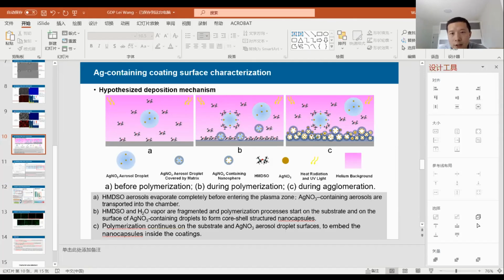For example, if we look at figure C, and look at the silver droplet, very close to the surface of the substrate, it's embedded very deep inside, so it takes more time. It's even harder for it to be released outside. So that's the reason for the long-term slow release. Okay. Thank you very much.